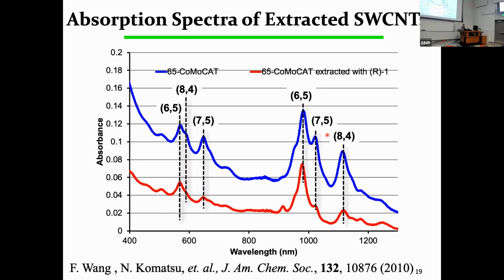And this is the separation for the (n,m) structure of the carbon nanotube. Before separation, at least three kinds of carbon nanotube are included. But after the separation, (7,5) and (8,4) decreased in this absorption spectrum, and relatively (6,5) was enriched. This clearly shows our host molecule also discriminates the (n,m) structure or the size of the carbon nanotube.